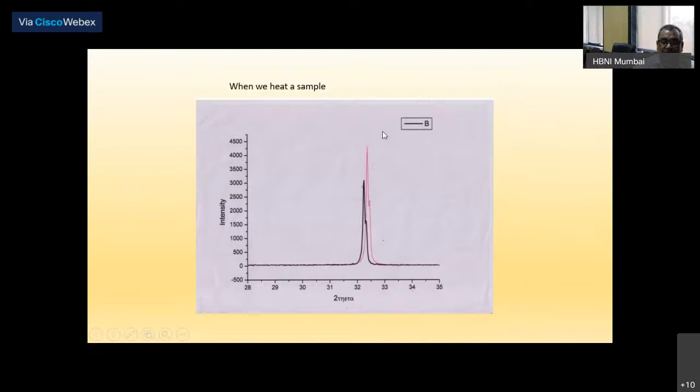And of course, this is where another important factor whenever we're designing a scattering experiment is the Q resolution. Here, with X-rays, the Q resolution allows me to see the difference between the K alpha and K beta lines of copper. This slight shoulder, these are K alpha, K beta lines. So this picture shows me that when I heat a sample, it expands, and the Bragg intensity goes down. You can resolve this piece.